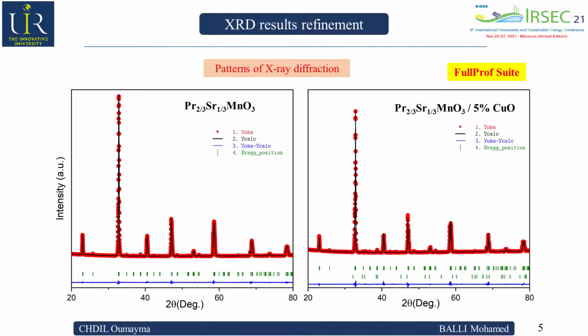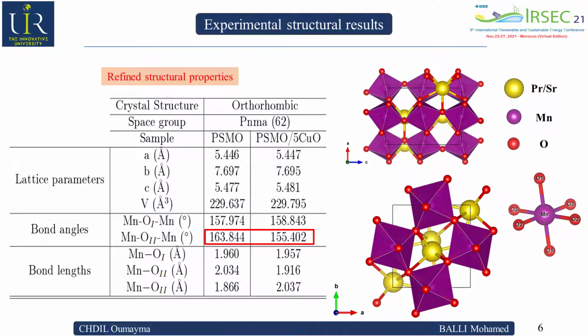The first figures show the X-ray diffraction patterns of the pristine and the composite samples. The first sample crystallized in the orthorhombic structure at room temperature with the Pnma space group, while in the second sample we can observe the coexistence of two phases. The refinement results for all samples are summarized in this table. The presence of the secondary phase leads to a clear structural deformation in the main phase, where the Mn-O-Mn bond angles are clearly modified.